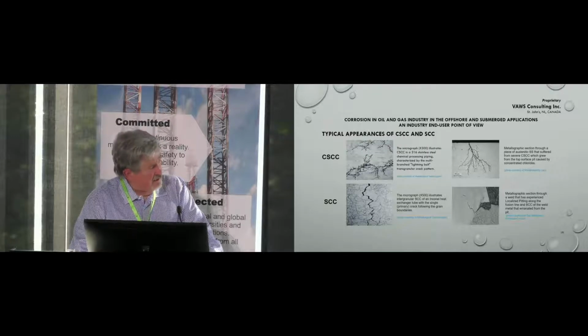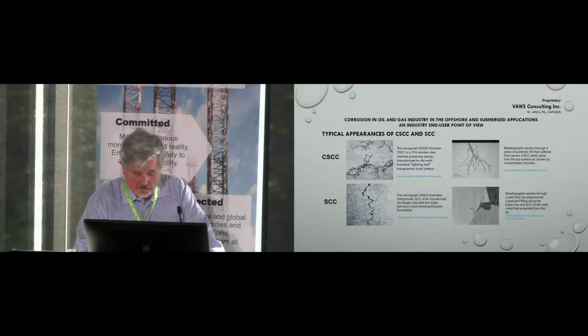Sulfide stress corrosion cracking is usually a single line, also starting from a pit on the surface usually, but sometimes it can develop within the metal itself. This is caused by hydrogen, which is permeating through the metal and combining into hydrogen molecules and increasing volume and increasing the stresses and blocking dislocations and all kinds of other tricks which hydrogen does in the metal, which is not desirable. Hydrogen is the only gas whose ions can liberally permeate through the metal compared to the other corrosive gases.